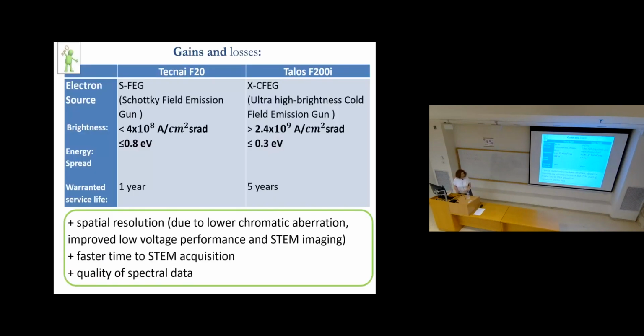Okay, so first of all, both instruments have a field emission gun, but what we had was the Schottky type field emission gun, and what we installed is an ultra high brightness cold field emission gun. First of all, the warranted service life of the Schottky is typically 1 year. That of the cold FEG is expected to be at least 5 years. So this is a sufficiently different lifetime.